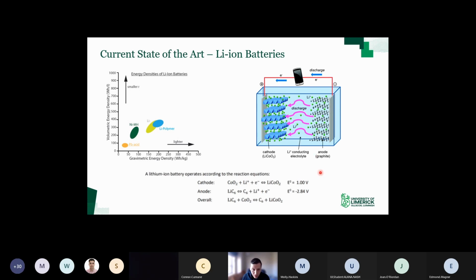So that works really well. But one issue is graphite does have a relatively low specific capacity. It has a capacity of 372 milliamp hours per gram. The reason it has a relatively low capacity compared to alloying materials is due to the anode half reaction here, which you can see is this middle reaction. For every 6 carbons, only 1 lithium ion can be accommodated. Okay, so that's not a very good ratio.